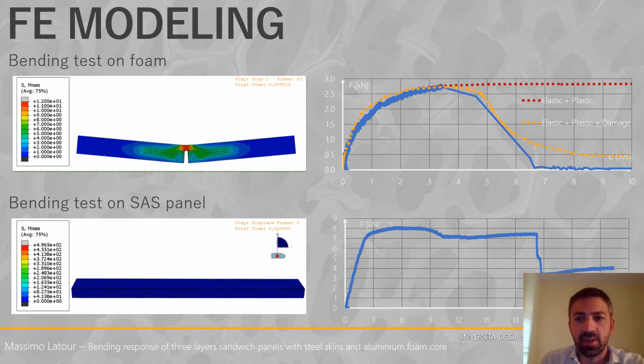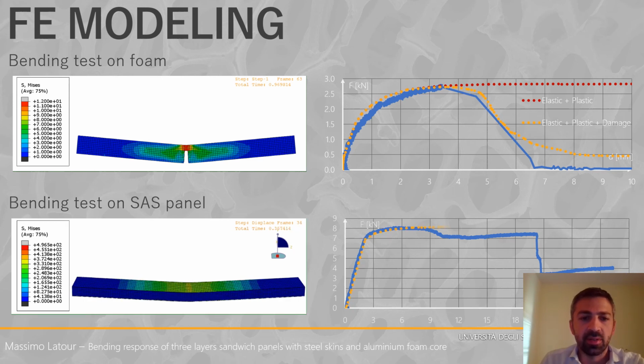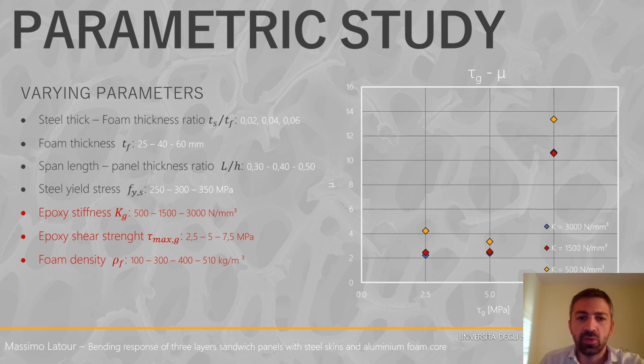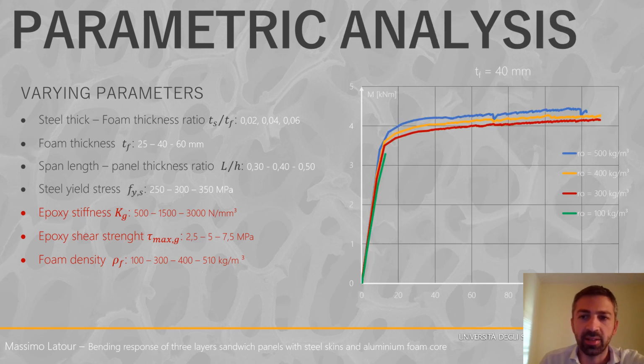This is both referred to the case of the aluminum foam only, as reported in the upper part of the slide, but also referring to the behavior of the aluminum steel sandwich panel, for which the model was able to provide a very accurate representation of the experimental response. The finite element model was used to perform a parametric analysis considering both geometrical and mechanical parameters. The parameters that were shown to be very important for this type of sandwich panel, as expected, were the glue mechanical properties, the glue strength and stiffness, and also the foam density. This is because the foam density is mainly related to the mechanical properties of the aluminum foam. In particular, the epoxy shear strength governs the ductility of the panel, as shown also by the experiments, that high bond strength is typically required to have high ductility.